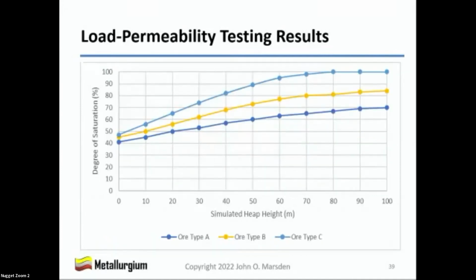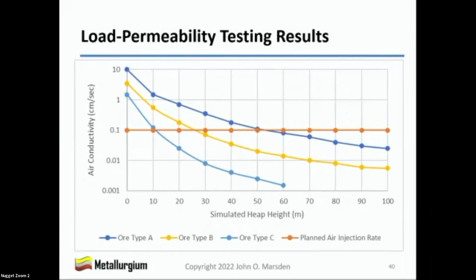If we go to the next slide, this shows the degree of saturation on the y-axis in percent, so this is the proportion of the voids that are filled with liquid, and the simulated heap height again on the x-axis. You can see the dark blue line on the bottom shows the degree of saturation in the ore type A going from 40% up to about 70%. Pretty reasonable. And then the next slide shows the air conductivity in centimeters per second against simulated heap height. The red line in this case is the planned air injection rate. So you can see here for ore type A that just over 50 meters, the ore type A is not able to be air permeable at the rate planned.